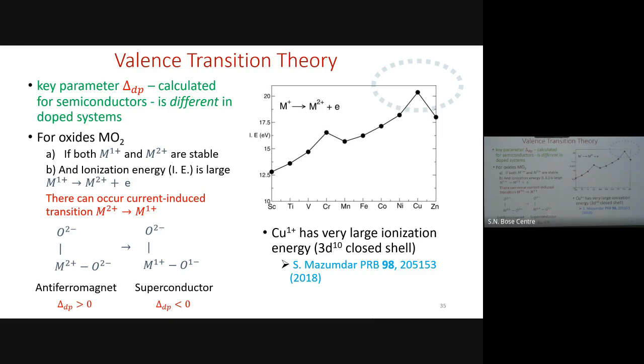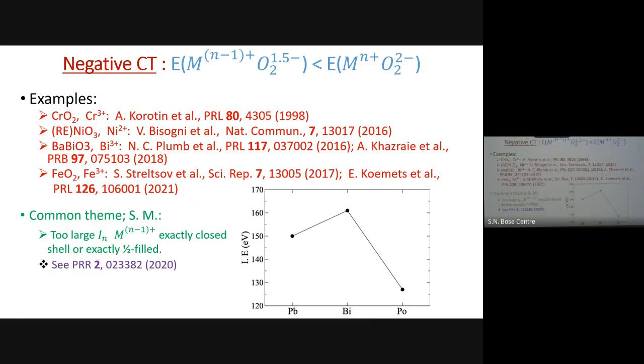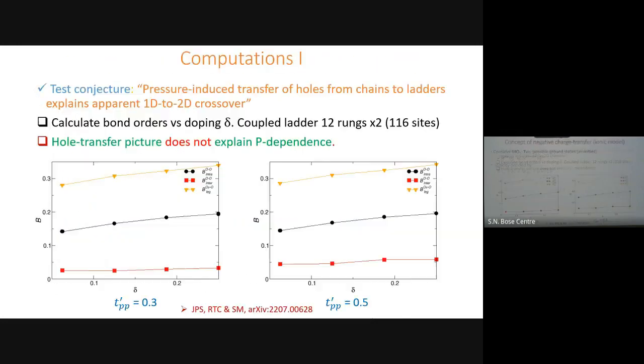I have to prove to you it's a superconductor. That's my claim. We haven't; that's not part of this talk. But the system is now a quarter filled band of oxygen. This is closed shell. It's not taking part in transport anymore. If this is true, I should be able to explain the dimensionality change that people see experimentally. We are calculating bond orders. We showed that with doping change, there is no change in dimensionality. This is what people are hoping.